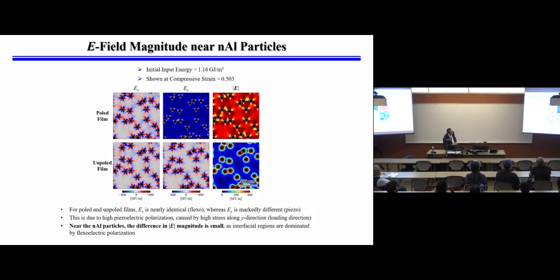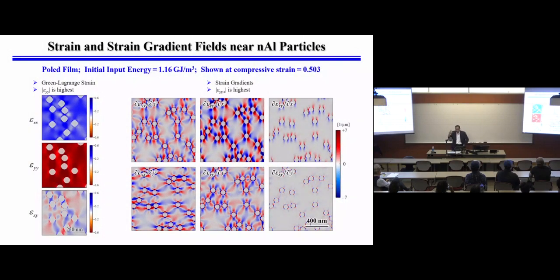So this is a detailed look at it. The E field, the horizontal component, the vertical component, the magnitude, poled and unpoled. Horizontal is pretty much the same. Vertical is different because the piezoelectric polarization is in the vertical direction. And then the overall E field is different. But again, locally around the particles, even with just pure flexoelectricity, the E field can be very high. That's where you have the problem, or you can take advantage of the effects.